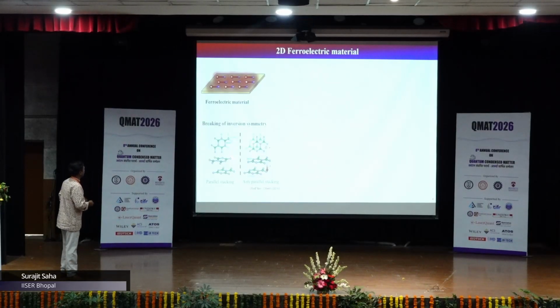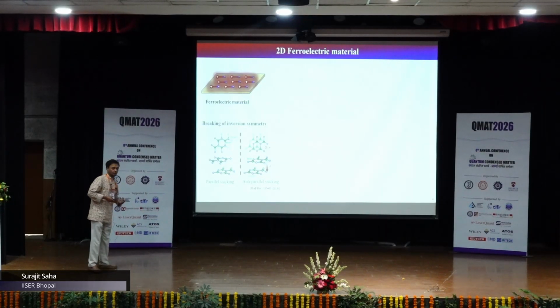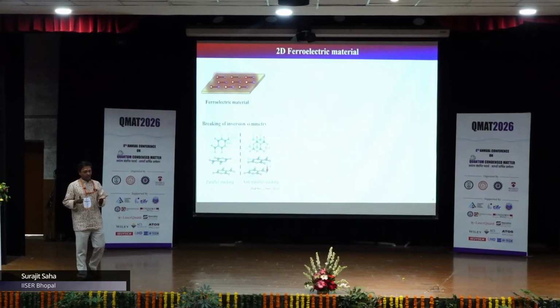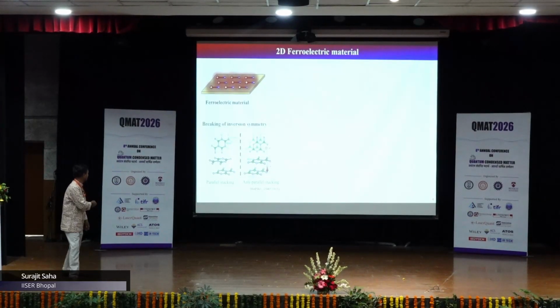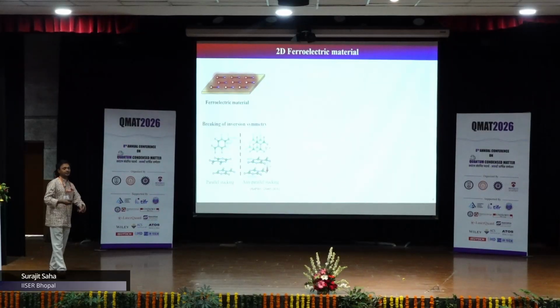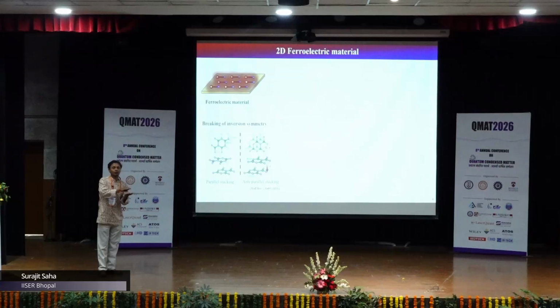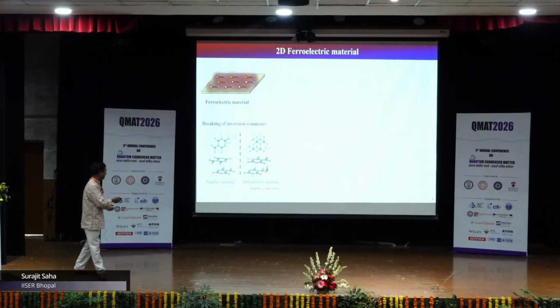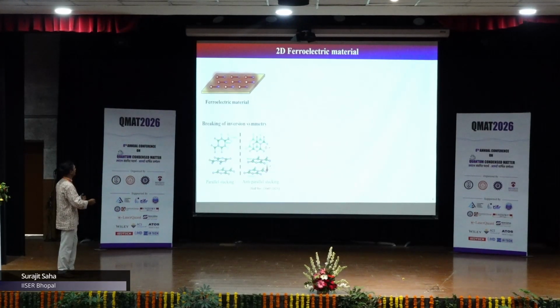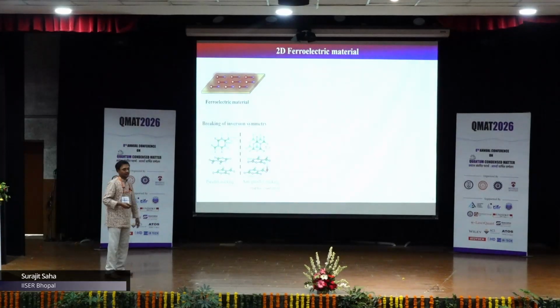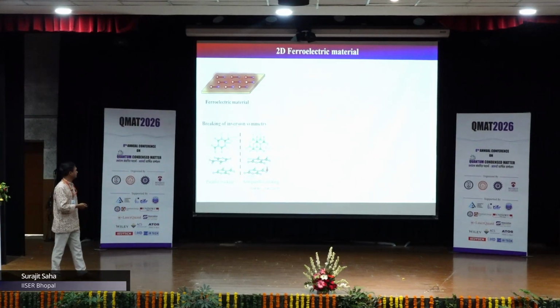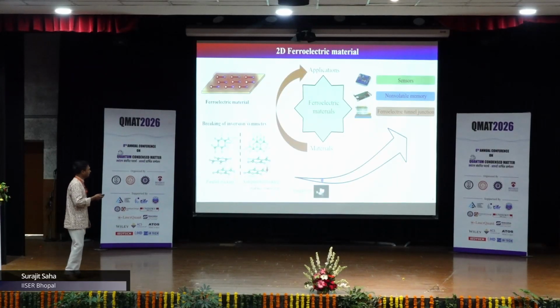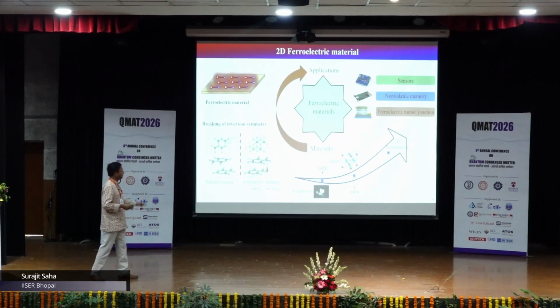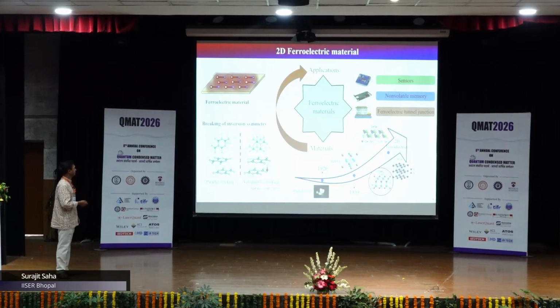Now, this is an example taken from hexagonal boron nitride. If the boron nitride layers are stacked in the parallel configuration, which is the first stacking here, that gives us net zero dipole moment. But on the contrary, if you have a slide by about one third of the lattice constant, then it gives this anti-parallel stacking, and that's where we actually see some polarization adding up. And similarly, there is a whole variety of other 2D materials that have been drawing attention over time, apart from the historic 3D systems. So indium selenide is something that I'm going to discuss.